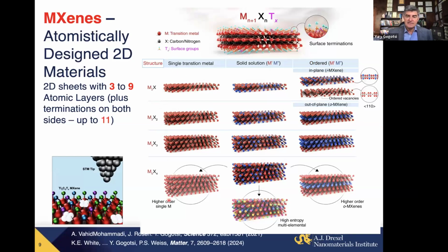So we can have simple MXenes. It's like a slice of sodium chloride lattice of conventional cubic carbide. We can have atomic sandwiches, where one metal is on the surface, for example, moly or chromium, and another, like titanium, is in the middle. We can make materials with alternating atomic columns of elements, or etch away one of them and have atomically thin trenches on the surface, vacancy trenches. And of course, we can put different functional groups on the surface, which will determine to a very large extent the surface chemistry. So basically, we learn how to atomistically design new materials, not take from nature what is given, but mix it and chemically in a vial make new materials.